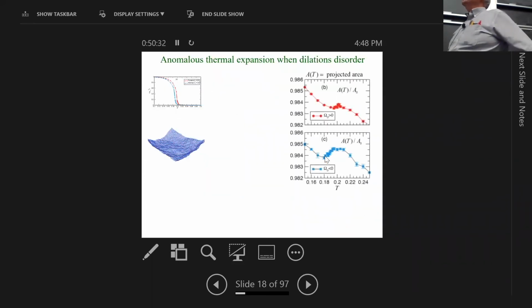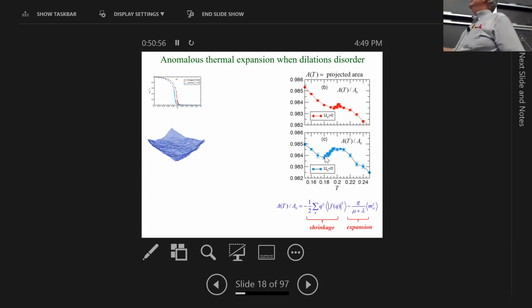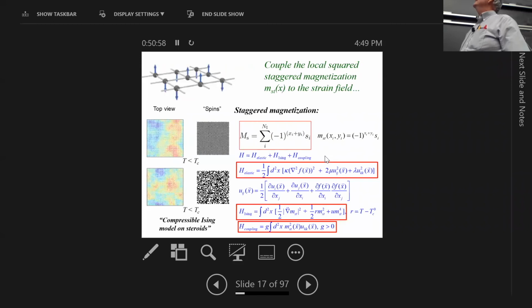You can study lots of interesting things, but one of the most interesting for us is the thermal expansion. Remember that thing was always negative? This is the area divided by some reference area. It's dropping as a function of temperature here. At the transition, it stops, it doesn't drop anymore, it goes up. And that's the effect, we believe, of this coupling constant G that I had in the previous slide. It says that when there's antiferromagnetic order, the packing in a sense becomes more efficient. And when you lose it, the thing swells because it doesn't pack well.